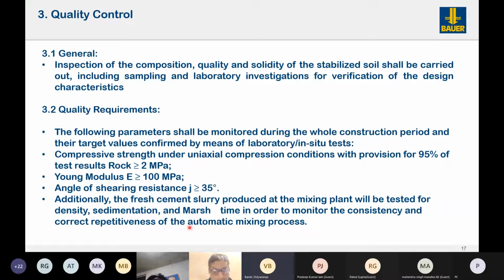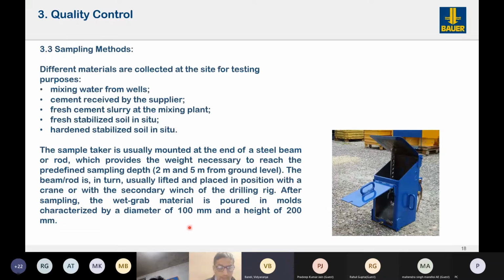Apart from that, the cement slurry has to be continuously tested for density and sedimentation, and the bentonite has to be tested for its marsh cone values, viscosity and density also. For sampling, we have different techniques. This is called a wet grab sampler, wherein once the DSM column is installed, we are able to collect the soil sample from different depths and cast a mold from the wet grab sampler of 100 dia and 200 height. We will then do a compressive strength test to ensure that the strength parameters are achieved.